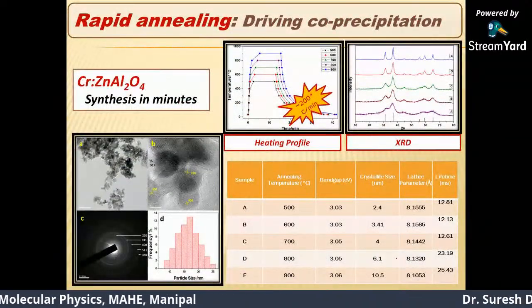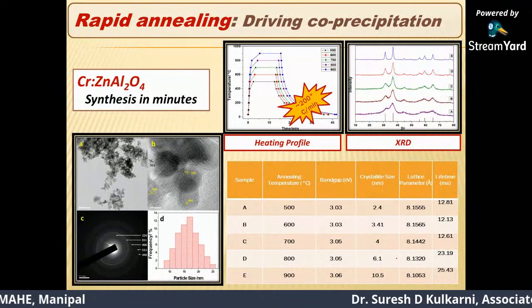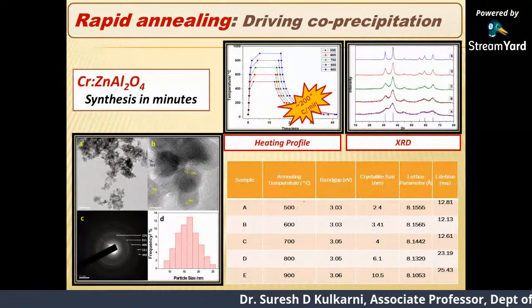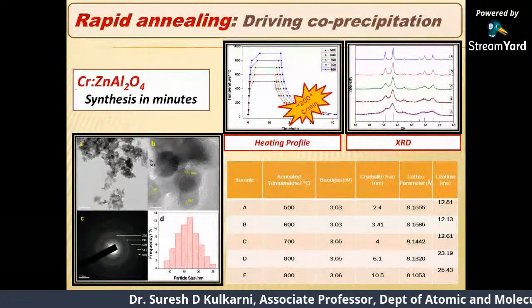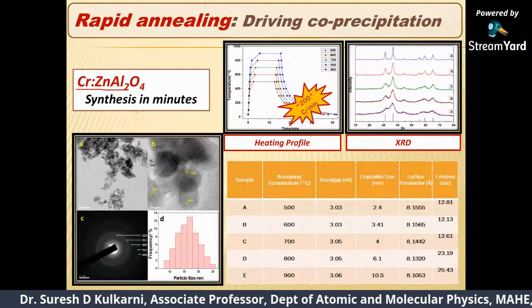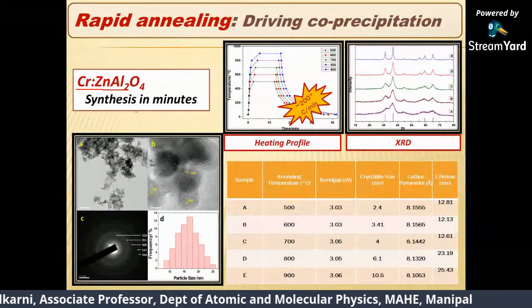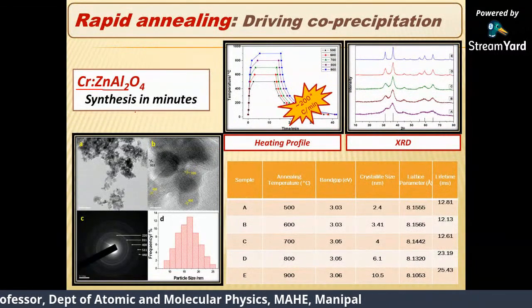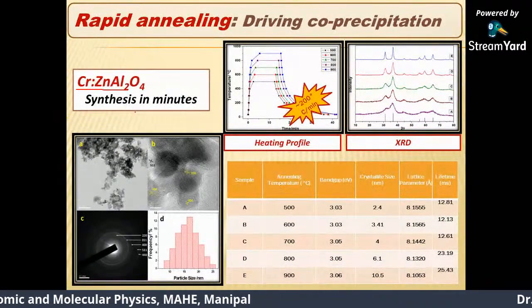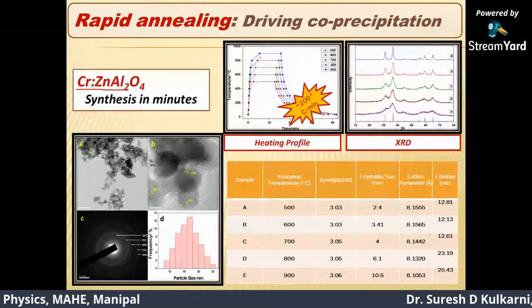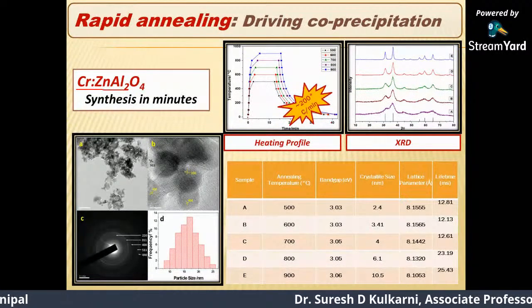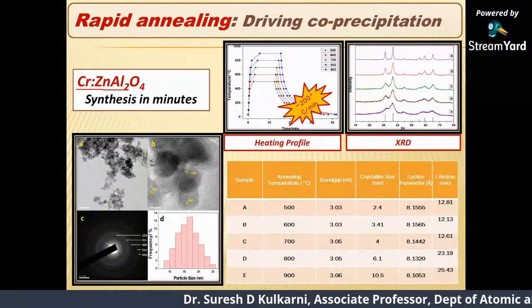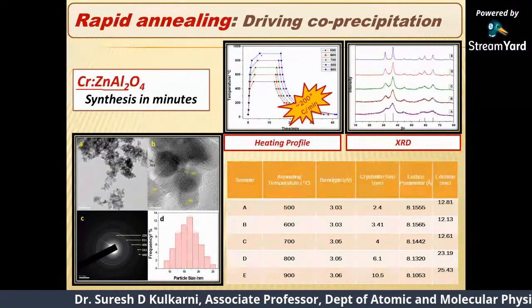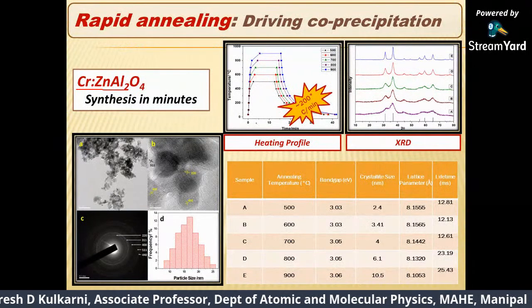So what we have done is, we have earlier prepared chromium doped zinc aluminate using a co-precipitation method. The precipitate was put under the rapid annealing system, and you can see the heating and cooling cycle is like this. From room temperature, within a few minutes I can reach, say here, 900 degrees in about 4 to 5 minutes.